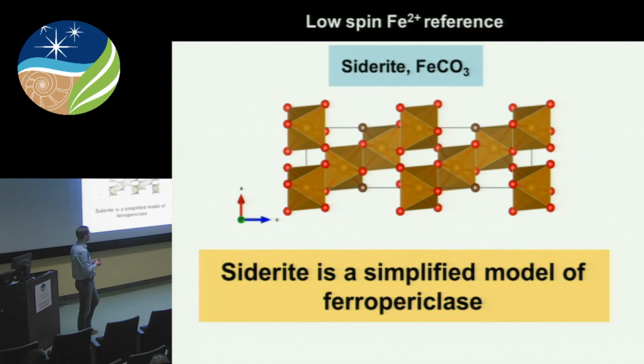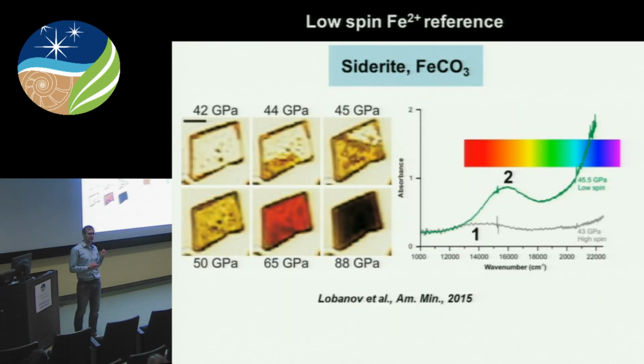What I want to say here is that I propose to use other minerals as sort of models of the lower mantle minerals. And here, siderite, in my opinion, and that's what I will try to convince you, can be used as a model of ferropericlase. The reason is simply because siderite contains exclusively Fe2+ that also sits at an octahedral site, just as in ferropericlase. But most importantly, siderite has an optically apparent spin transition. Here on the left, you can see optical photographs of siderite as a function of pressure. And basically, as you squeeze your mineral up to about 45 GPa, nothing happens to its color. It remains transparent.